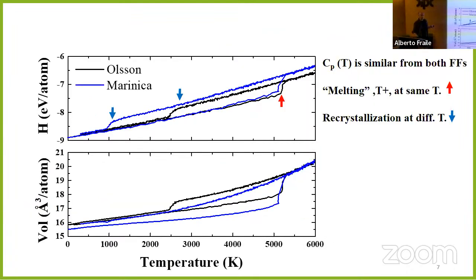But the reason to use 2 potentials is also that it's tricky to know when the potential will be good or not for these kinds of simulations. We want to model properly the target, the material itself. So we want a potential that gives reasonable mechanical properties of the target. But also the thermodynamics is important. For example, here we see that with these 2 potentials, we have more or less the melting, this jump in enthalpy, at the same point, more or less 5,000. Okay, it's overestimated, as is always the case in general, but the melting is more or less the same.